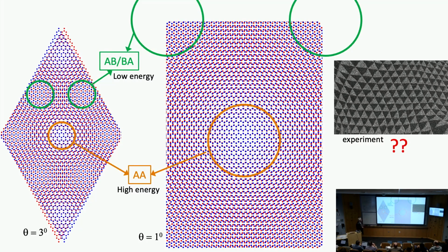Where are the atoms? If you look at the pattern of superimposing a blue layer on top of a red layer, two layers of graphene, without any relaxation, you see regions where the two lattices match almost perfectly. Those are called AA regions and correspond to high energy stacking of the atoms. You see other regions where the top layer and the bottom layer are basically perfectly moved relative to each other, so that the top layer hides only half of the atoms of the bottom layer. So you see here all the blue atoms, but only half of the red atoms. And this is called AB or BA regions. Those are equivalent by symmetry.